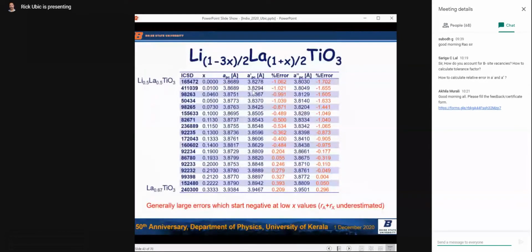We did the same sort of work with lithium lanthanum titanate. There were way more data points. We didn't make any of these, all from the literature, but it emphasizes the point even more. This stuff is reported with long-range A-site ordering. And you can see, again, large negative errors at low X values that increase the positive as you go up, right? Same thing here, right?